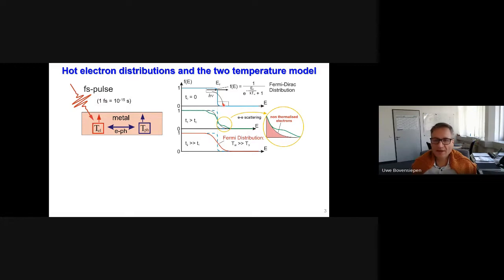And since there's electron-electron scattering as a very likely interaction process going on, we have quickly after the excitation this non-equilibrium washed out distribution. And if we even wait a bit longer, electron-electron scattering gives rise to a Fermi-Dirac distribution again. However, the electronic temperature is expected to be way larger than initially. And now we can discuss whether it's only the electrons that have interacted at the time scales, or we have also to take lattice excitation or spin waves into account. And there's a very simple model that I will introduce now that considers that the hot electron temperature interacts via electron-phonon coupling with the lattice.